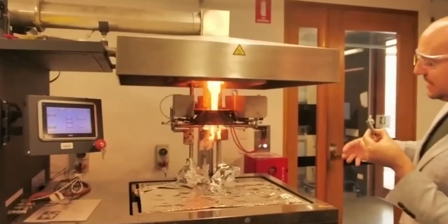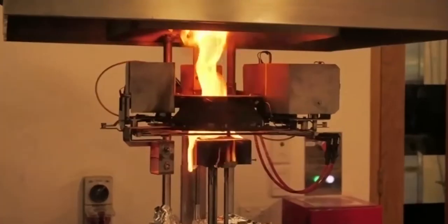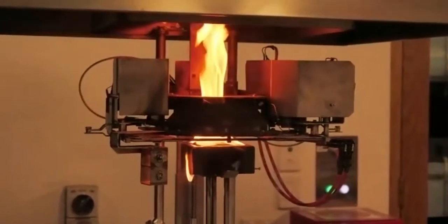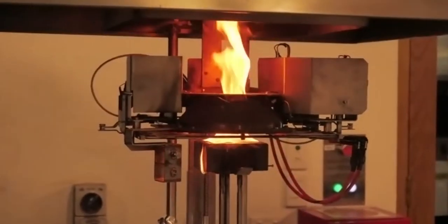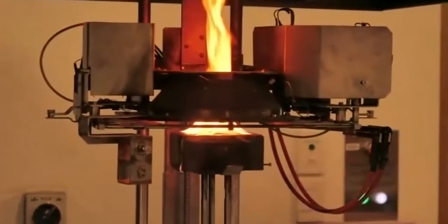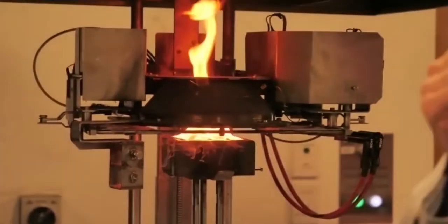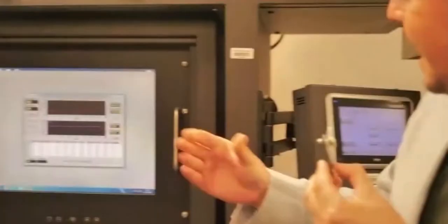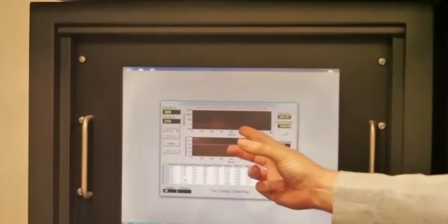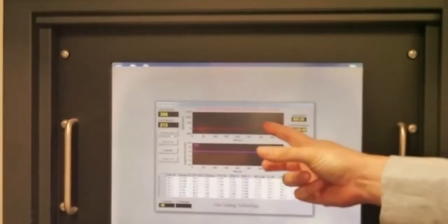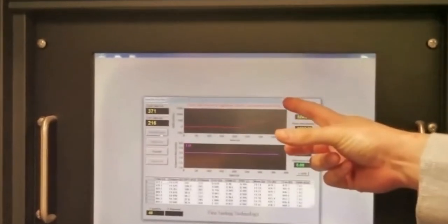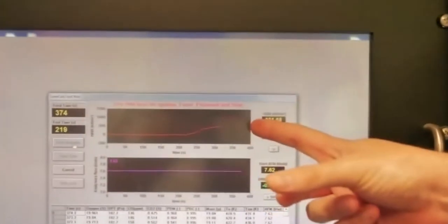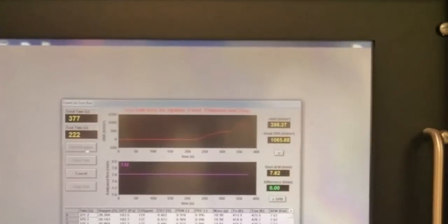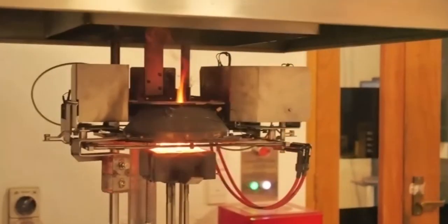Now you can see something that occurred that is really common in this type of material. For example, this is a really, really dangerous composite. It is mainly polyethylene. And what you can see is that it starts dripping and melting. Okay. So finally, you can see here how the burning process is taking place. Essentially on this curve, we see how the heat release rate increases to a peak and at some point it starts to burn out once the fuel gets consumed, which we can see visually back here with less intensity of the flames.